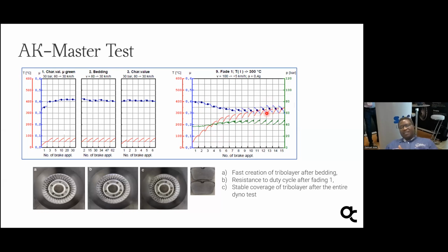And the next stage after fading, we see the recovery. It recovers quickly back to close to 0.4 coefficient of friction. But this was not shown in this picture. But at the end, you see the surface of the disc is darker, which shows the tribo film formation on the surface. And we see the part, which is very, very good. That is what we desire for our brake friction couple.